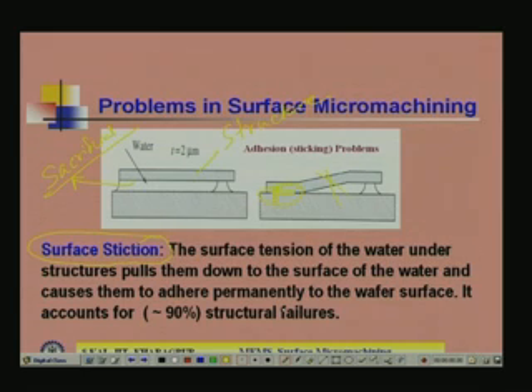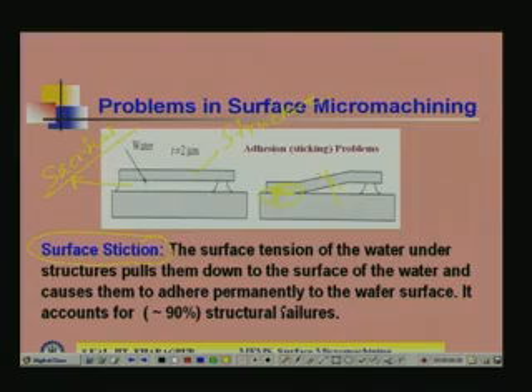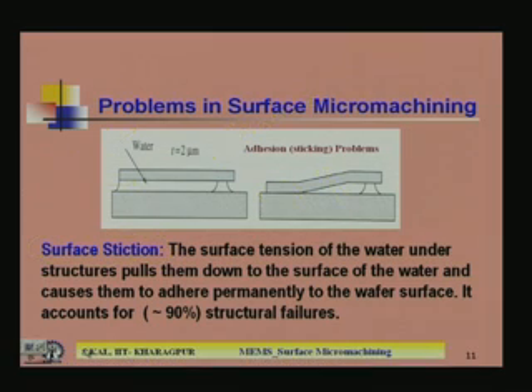Nowadays, there are two solutions people have thought about. One is that in the etching solution, you add some chemical so that the surface tension will be less and less. That is one, because it is basically because of the surface tension. The second one, you modify the structure at the mask level so that you can create some small bumps in some of the locations, which will prevent bending down of the structure. That is shown in the next view graph.